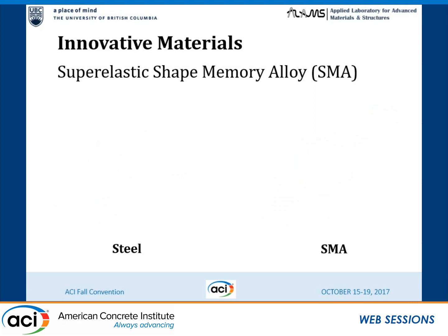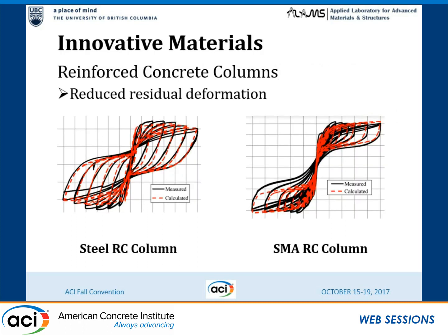This kind of material does exist and is called super-elastic shape memory alloy — there are different types available and they can be purchased on the market. Looking at element-level performance under reverse cyclic loading, conventional columns show large permanent deformation, whereas structural elements using shape memory alloy reinforcement tested under shake table or reverse cyclic loading show flag-shaped hysteresis, where residual deformation is significantly minimized and permanent damage is greatly reduced.